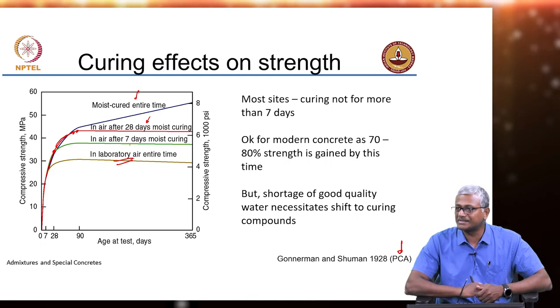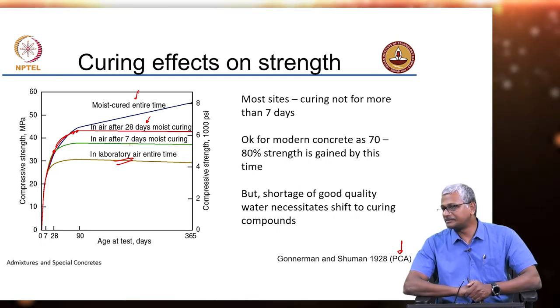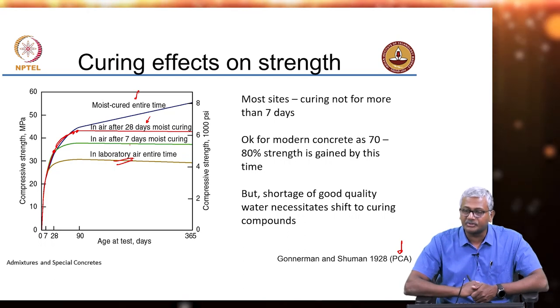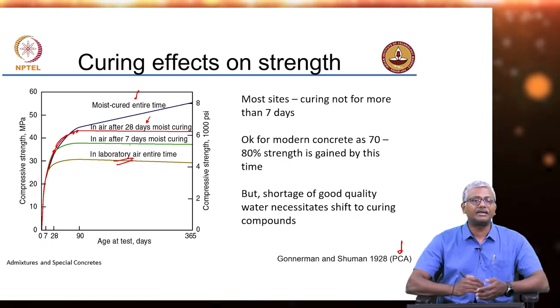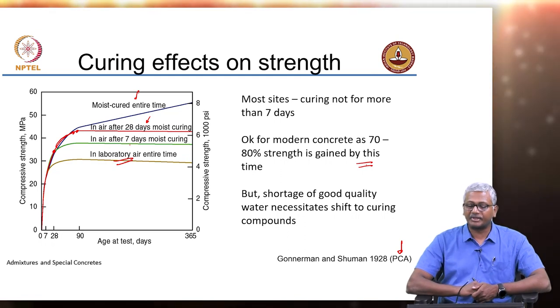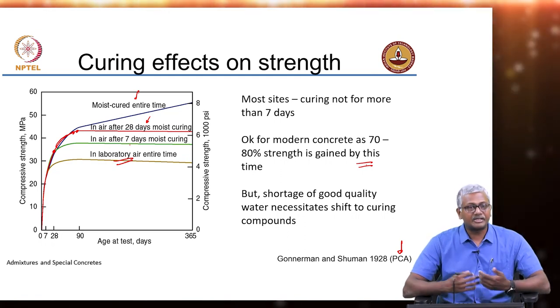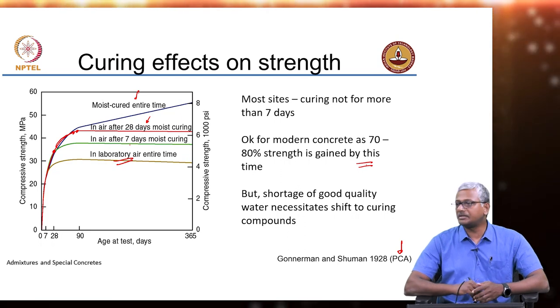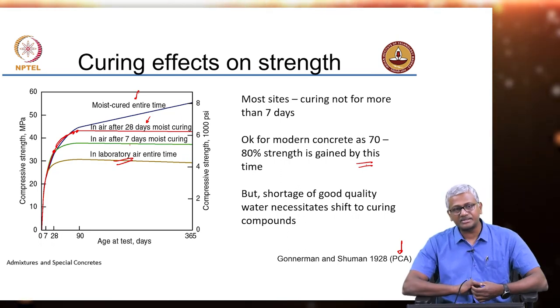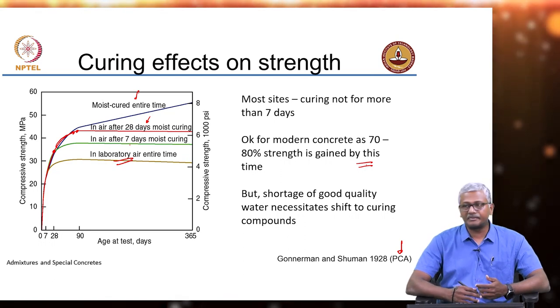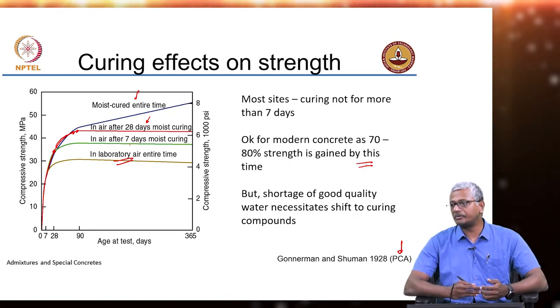If your concrete cubes are not getting cured, people are obviously going to say it is not acceptable. You need to ensure that you provide a curing system which can take care of concrete at least until 70 to 80 percent of strength has been gained. We typically follow site curing for 7 days because most concretes designed with modern cements tend to gain up to 70 percent of their strength by that time.